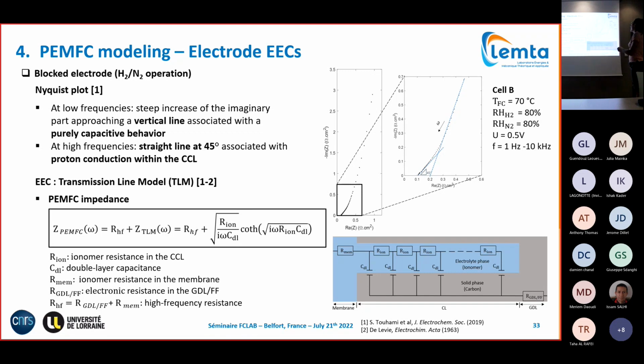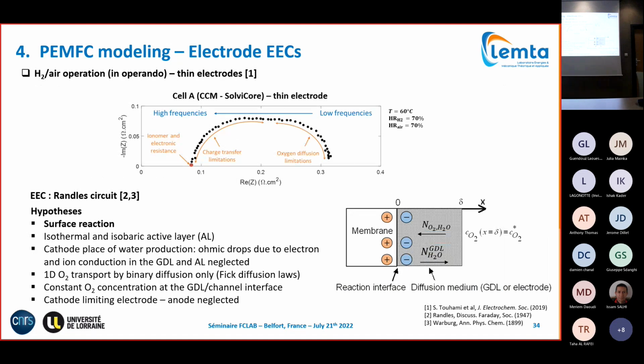characterized by a steep, more or less vertical line below the frequencies associated with electrical double layer charge storage at the interface, pore space between the carbon and the electrolyte, and a 45-degree line at the highest frequencies associated, in this case, with ion conduction inside your ionomer phase, inside your agglomerates of electrodes, through the electrode phase. And in this case the circuit corresponds to the shape, which is the same as for classical supercapacitors, the theory that was derived by de Levie. Now, just to remind you, here's the transition between supercapacitors and fuel cells.